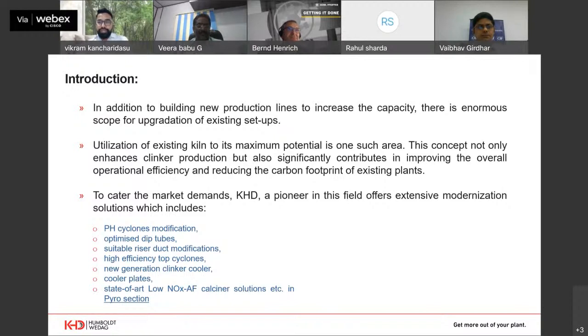The modifications in the preheater system include the latest high efficiency preheater cyclones, whether it is a KHD preheater or a competitor's preheater. We are able to do the modifications in cyclones. There will be some tailor-made modifications, optimizing the dip tubes to improve collection efficiency as well as reduce pressure drop, suitable riser duct modifications in the preheater, and high efficiency top cyclones to improve the overall dust collection efficiency of the preheater system, and new generation clinker coolers. And if it's a grate cooler, keeping the existing structure as it is, the complete moving grate can be replaced with the latest grate plates, and a state-of-the-art low NOx alternative fuel calciner, and there are other solutions as well.